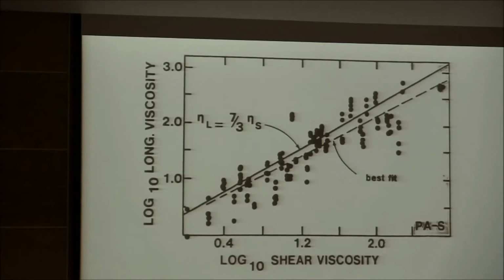Okay. We also know that the tensor of the stress which is involved at the glass transition is not important for us, because no matter how we measure the viscosity of the liquids, if we measure it in simple shear, or if we measure it in so-called longitudinal viscosity, so that we have a volume component of deformation, these things are decompressing. There is a volume component of deformation. As they come up, they become less dense. It doesn't matter. We get a very simple relationship between the two.